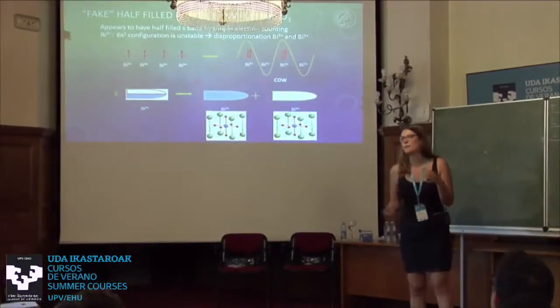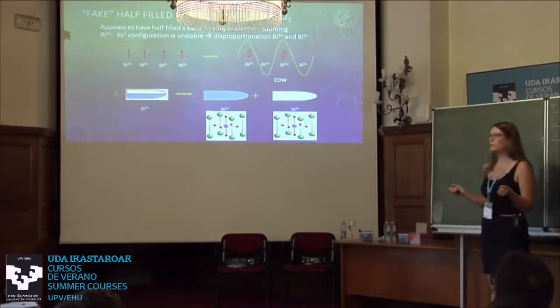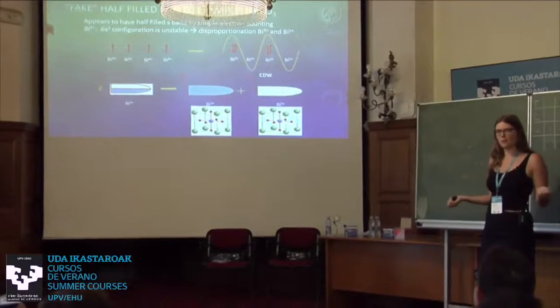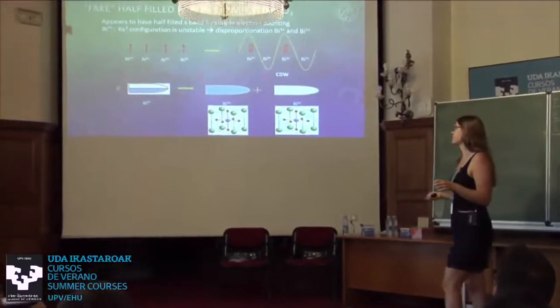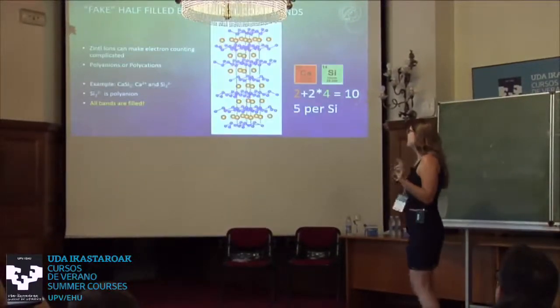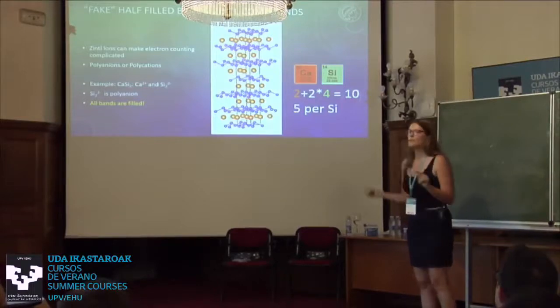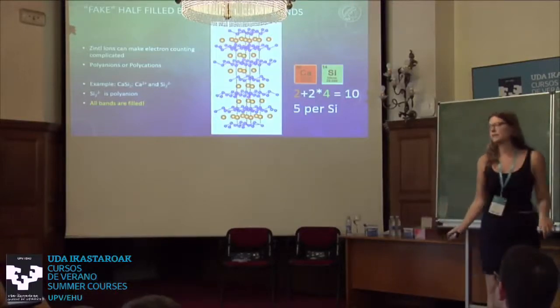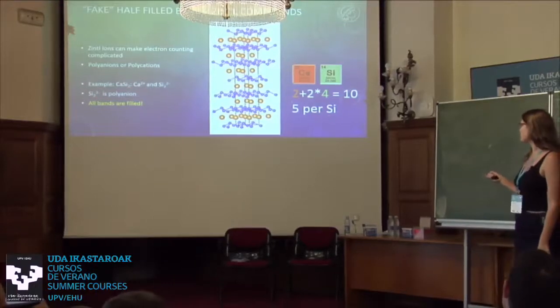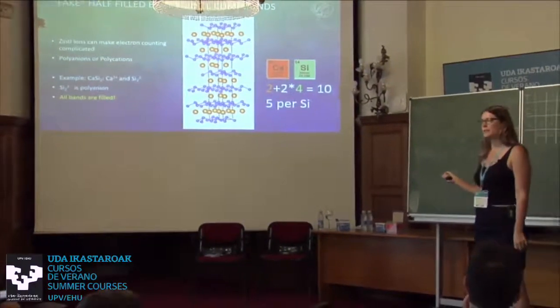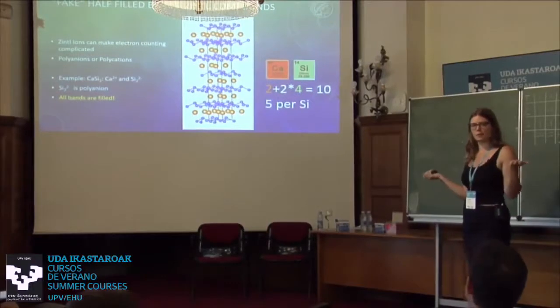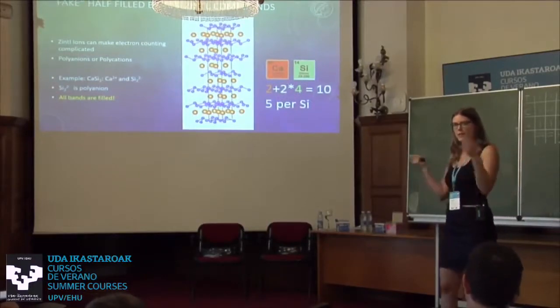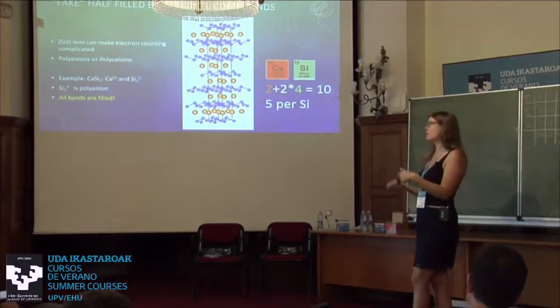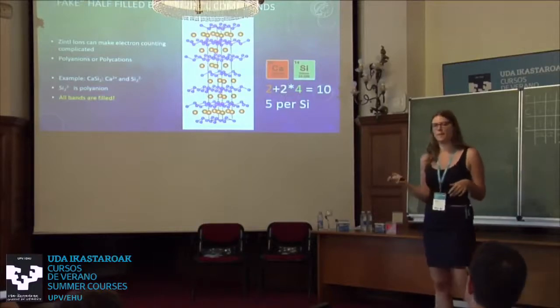So if you think about non-symmorphic compounds, this is some kind of trap we can walk into, that a compound might appear to be half-filled, but if you look carefully, it's not. Okay. And there are more of those fake half-filled bands. One is what I showed you already before, this interphase calcium silicide, where you would count 5 electrons per silicon. If you know that 2 of them are S electrons, you would think you have 3 in the P electrons, which would be a half-filled P band. However, because of the bonds, this is not happening.